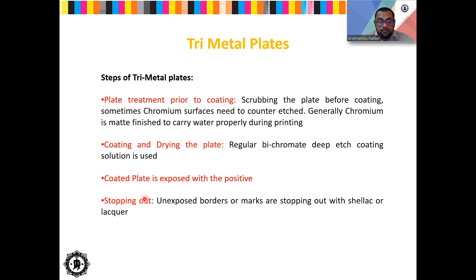Next, good sharp positives are required, but for the best results, half tone positives should be made a little higher than for deep etch. By higher, it means that all tones should be lighter or sharper. The reason for this is that in etching through the chromium layer after the image has been developed, there is a slight sidewise etching that enlarges the dot. So it means lateral etching. To produce the same tone values on the trimetal plate as on the deep etch plate, the half tone dots on the positive must be slightly smaller.